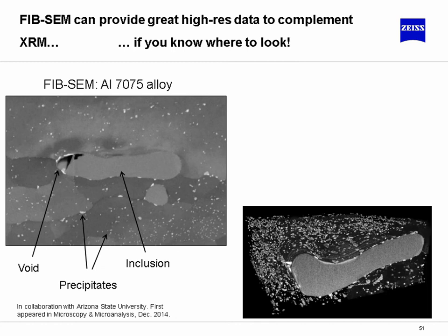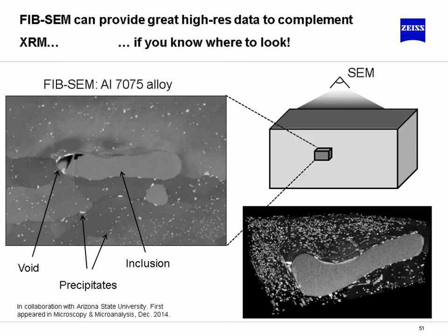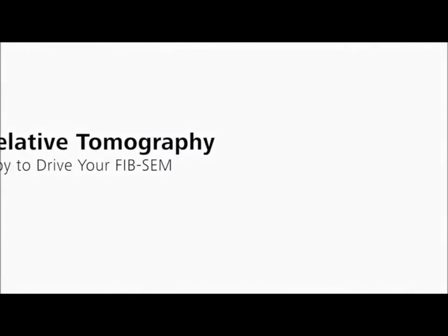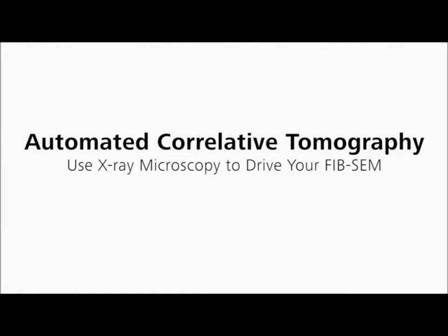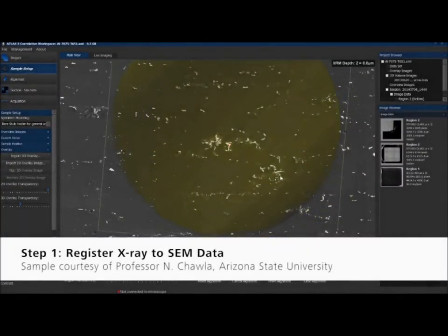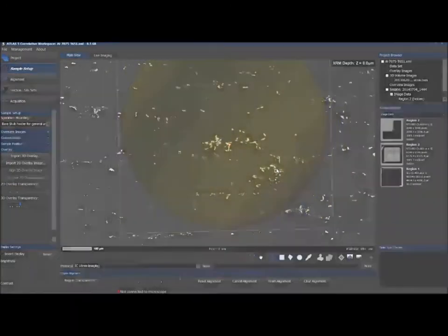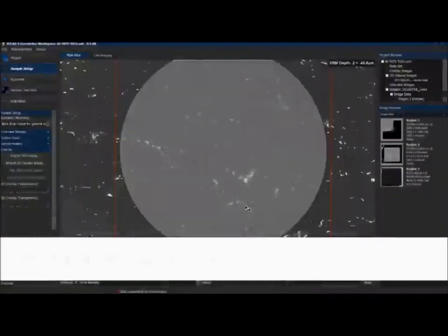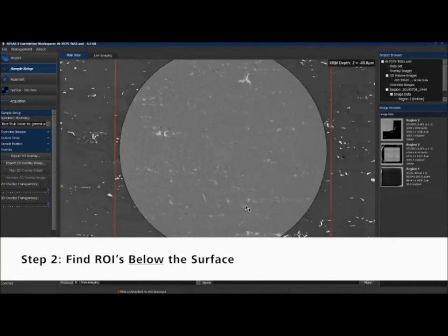So this technique was actually employed first to scan the sample with X-ray tomography, then moved to FibSem tomography, but we didn't do this blindly. FibSem, as Fabian showed just a moment ago, is a fantastic and diverse technique, and it's great if you know where you're looking, what you're looking for. So we basically have demonstrated over the past couple of years now a very efficient technique utilizing software known as Atlas V, which is an online direct control of the ZEISS FibSem, the crossbeam platform, to guide and automate this procedure of targeted FibSem acquisitions.